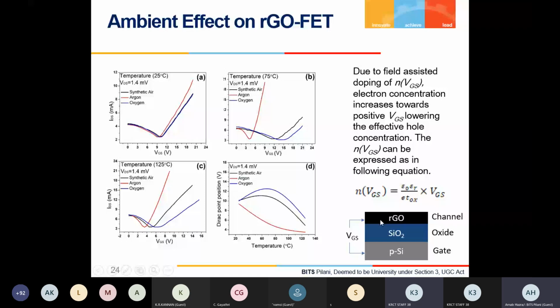Initially, the graphene oxide is p-type in nature because a lot of oxygen species was absorbed over the surface. So the effective electron concentration was reduced and hole concentration was high. So initially it was p-type in nature. With increase of gate to source voltage, the current decreased, and here the minimum point is called the Dirac point, and then onward current is increased. There is no significant effect of this ambient at this low temperature or room temperature, 25 degrees centigrade.